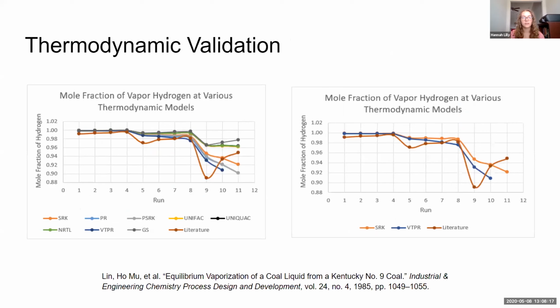In order to validate our thermodynamics, we put a flash after our reactor and plotted the mole fraction of hydrogen leaving the top of that flash drum against literature data. In the graph on the left, we can see the 8 thermodynamic models that we considered and compared to literature. The graph on the right shows the 2 with the smallest sum squared error, which were SRK and VTPR. Though VTPR technically had the smallest sum squared error, due to the computational time associated with using VTPR thermodynamics, we moved forward with SRK.